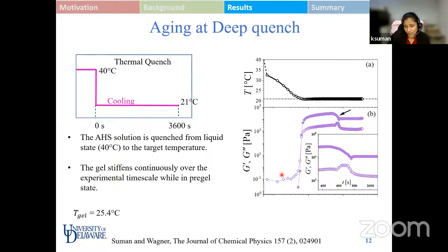Surprisingly, the modulus value, which was increasing slowly as in the shallow quench, is now accompanied by a sudden decrease at a certain time, which is indicated by the arrow over here. A zoomed part of this is shown in the inset, and we can see that the modulus value decreases by 3 times and then tries to saturate at a particular value. On the other hand, G double prime, which is the viscous component of the material, undergoes a weak overshoot and then also saturates.